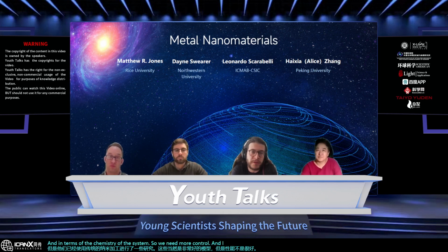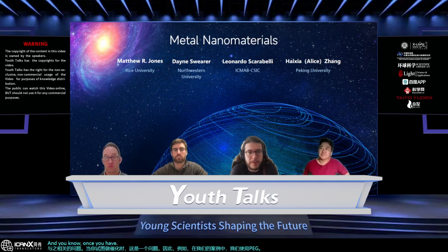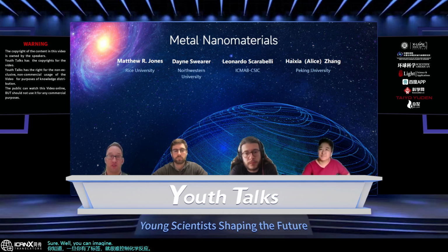I think that self-assembly is a possible approach, but the presence of ligands and all the correlated issues with that is a problem when you're trying to do catalysis. So, for example, in our case, we use PEG, and once you have PEG on top, it's hard to control the chemistry there. Well, you could imagine trying to rip the ligands off afterwards, once you had made the structure that you wanted, through plasma etching or something like that.